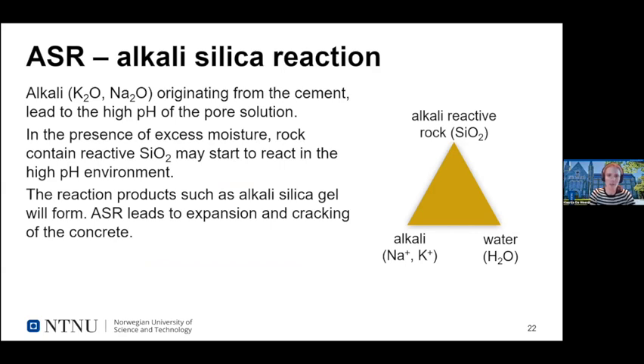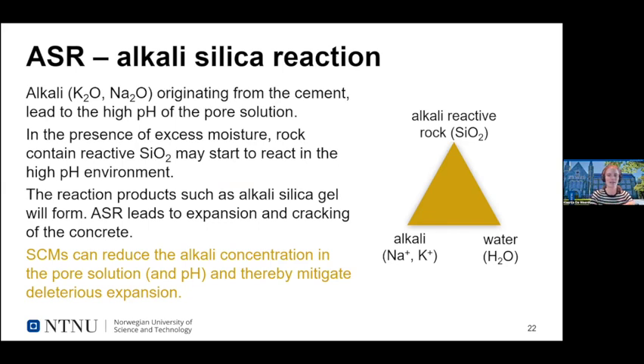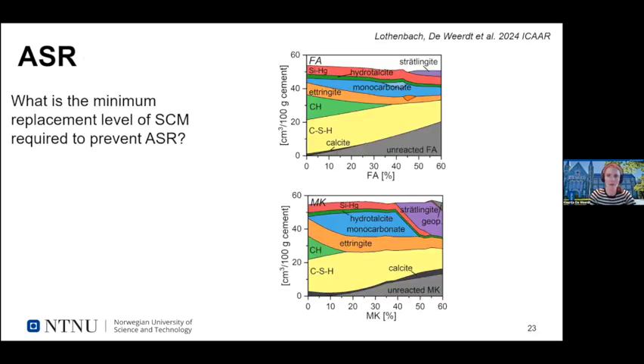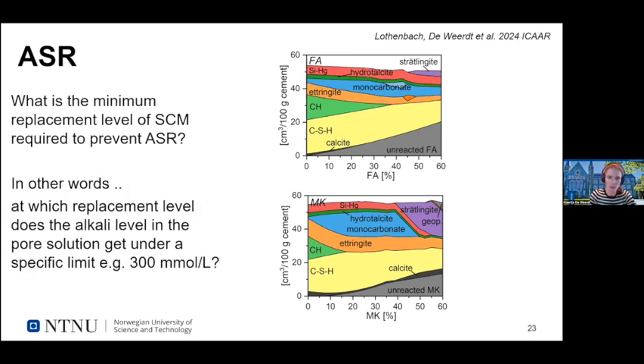So the role of SCMs when it comes to ASR is they can reduce the alkali concentration in the pore solution and thereby mitigate these deleterious expansions. So the SCMs will reduce the amount of available alkali for the reaction. And this is something Barbara and I wanted to look into in connection to a publication we wrote for the upcoming ICAR conference. We wanted to determine the minimum replacement level of SCMs required to prevent ASR. Or in other words, we want to know which replacement level lowers the alkali level in the pore solution below a specific limit. And here we assumed 300 millimole per liter.